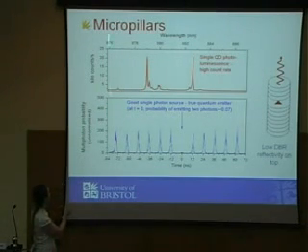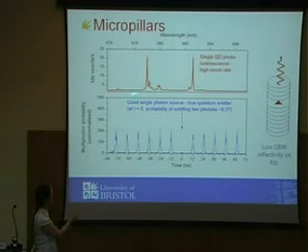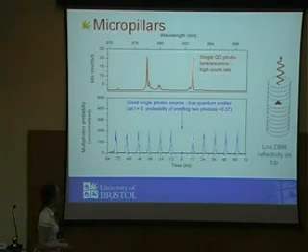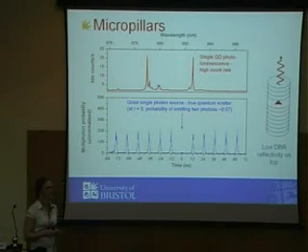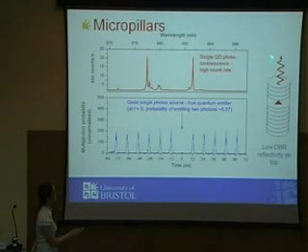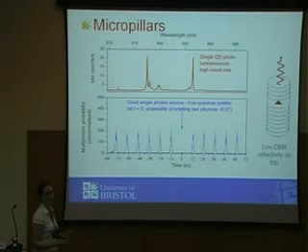Here I'm showing you some PL spectra from quantum dots inside the pillar. They appear at random places, but they're emitting into the cavity, and we have fairly high count rates of about 20,000 per second using an 80 megahertz pump laser. What we do with that signal is try to show that it's producing one single photon every time we put in a pulse. We take the emission, divide it into two, and detect with two photon detectors. This is called a Hanbury Brown and Twiss experiment.